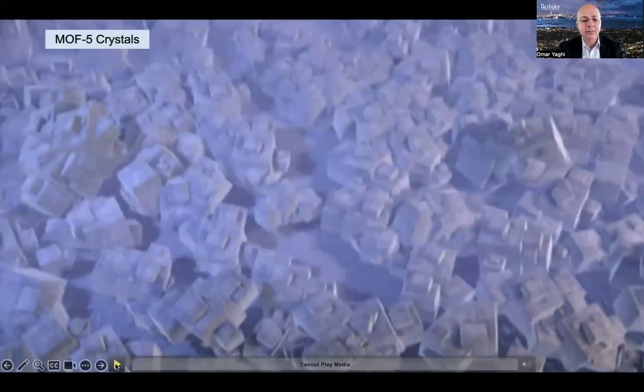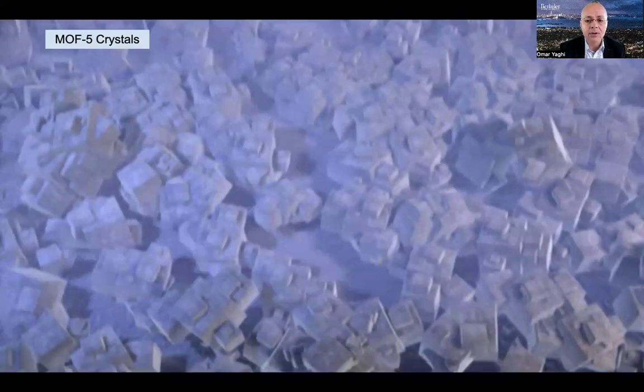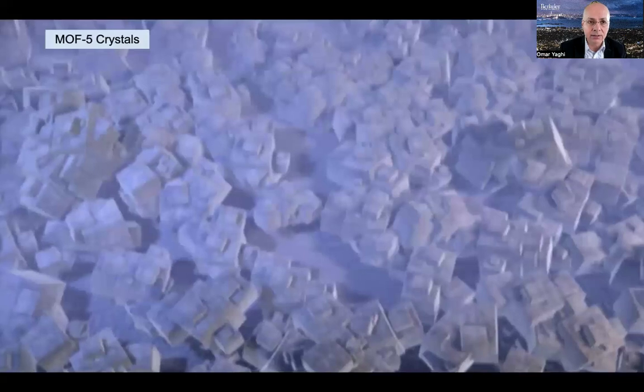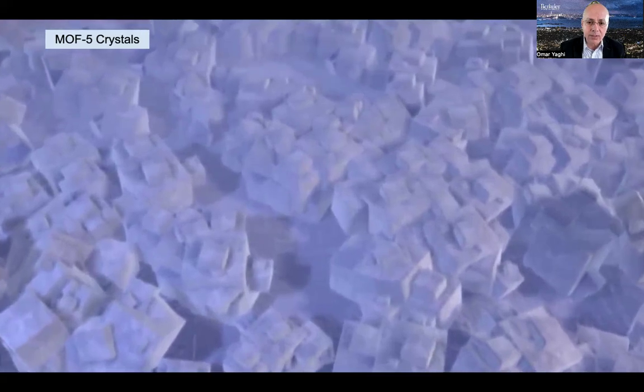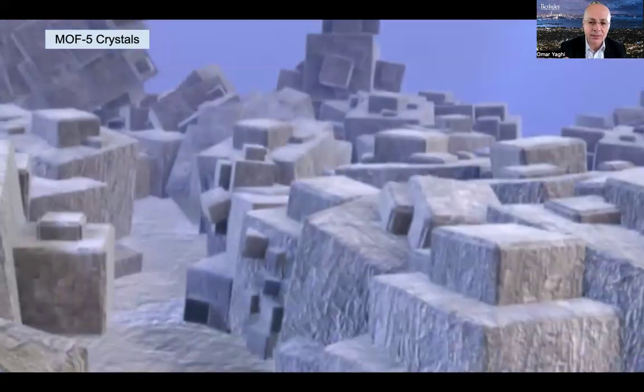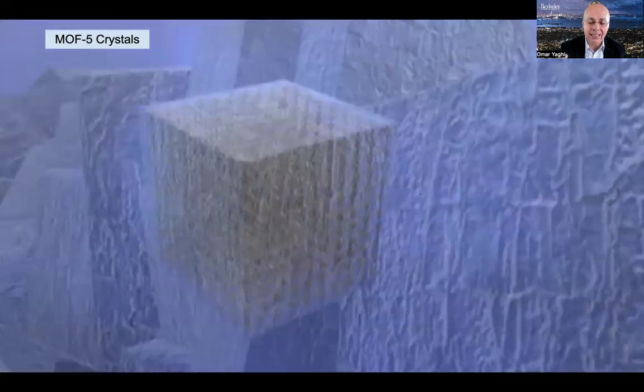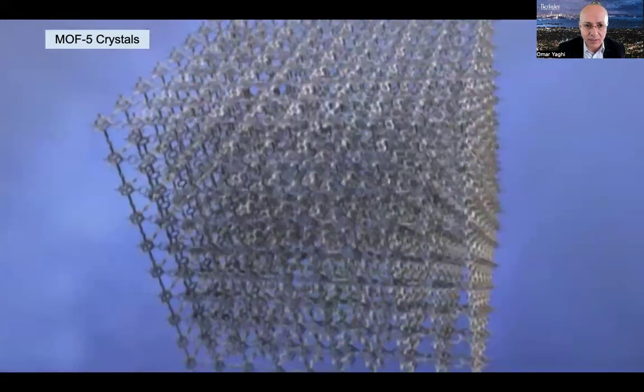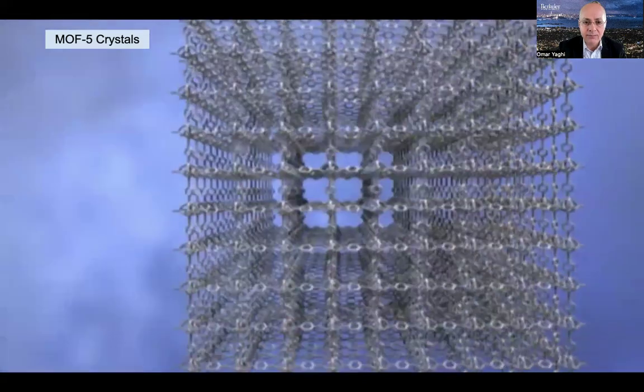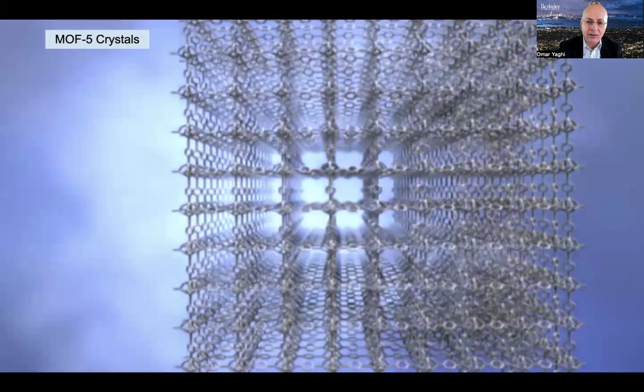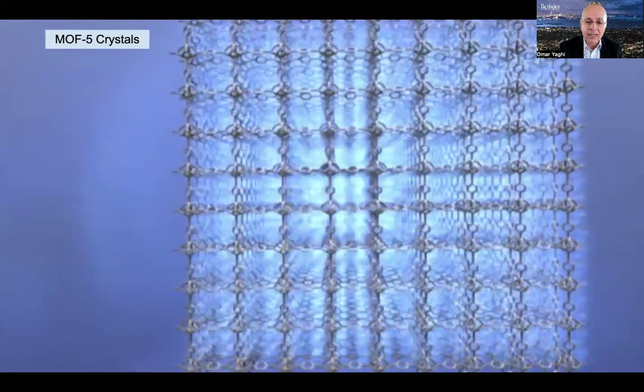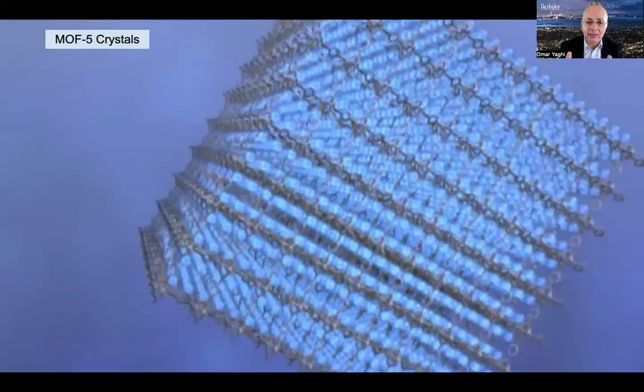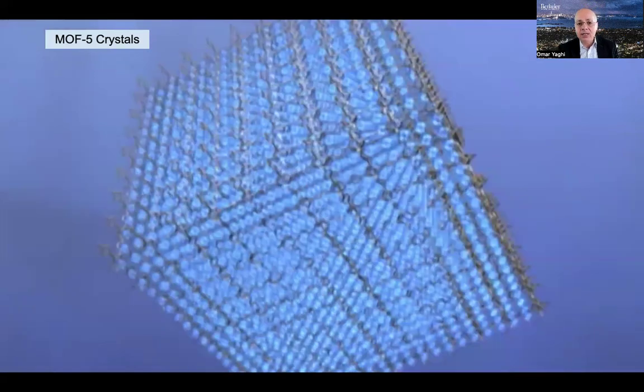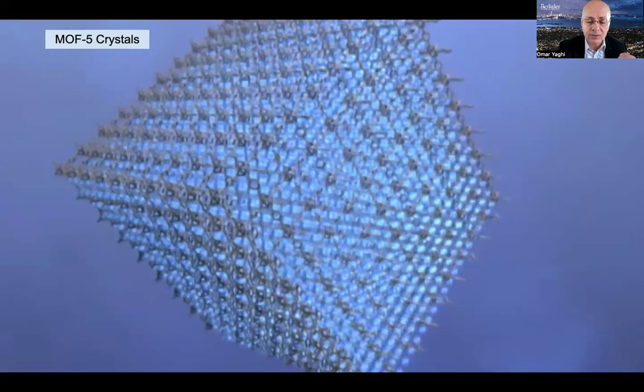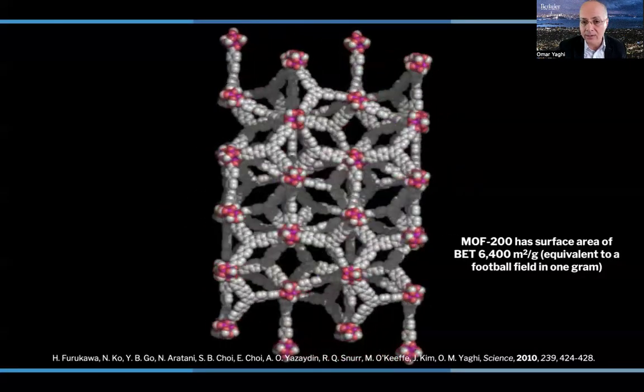I want to show, for some of you who are not familiar with MOFs, that MOFs look like, to the naked eye, baby powder, or granulated sugar. And in this movie, it shows that when you zoom in on just one granule, you'll find that on the atomic level, it's riddled with holes. And it's in these holes that gases that would fill very large volume could be compacted within the pores, as you see here. So in many ways, the inside of the granule has much larger volume than the outside, and they act like magnets, bringing in gases and compacting those gases within the pores. That's really how MOFs work, or how these reticular materials work.